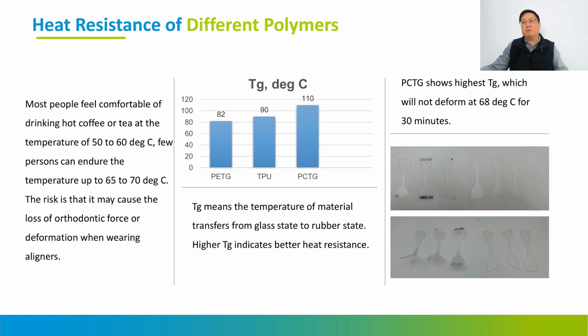Then let's come back to talking about the heat resistance of different polymers. If you use a higher Tg, as I said earlier, it means higher stress retention. And with a higher Tg material, you can drink hot water or hot coffee without deformation of the liners. We do a lot of experiments, such as putting the material under 68 degrees C for 30 minutes. Some of the material is already deformed, but if you have a high Tg, it means better heat resistance, and they are not deformed. So this is very important.